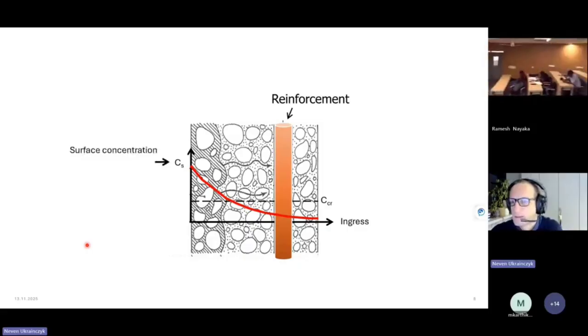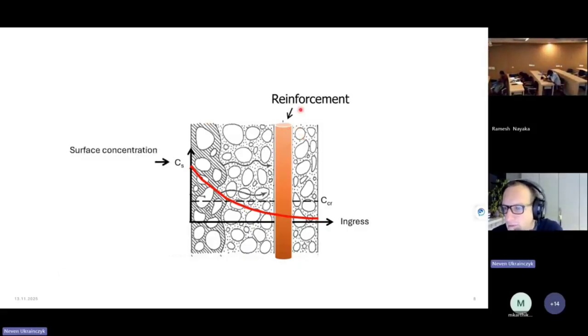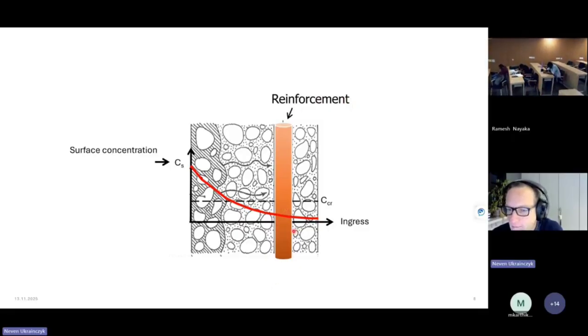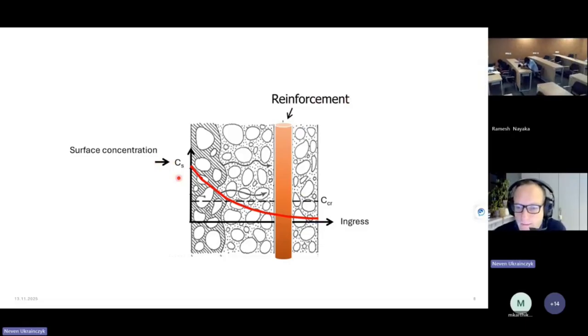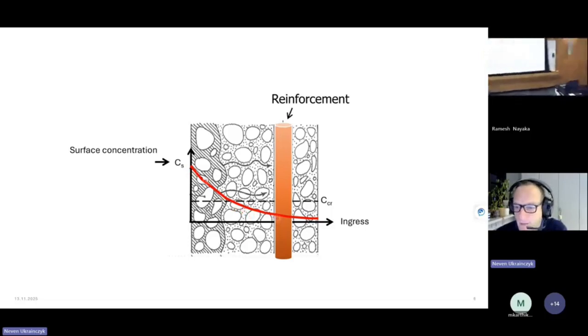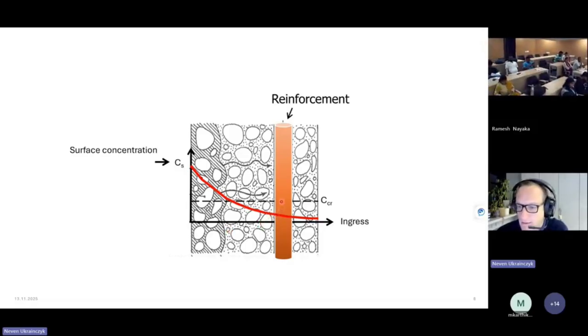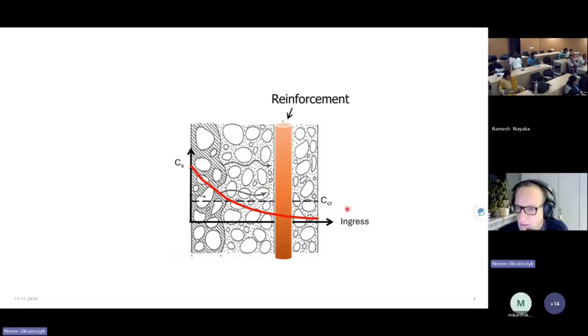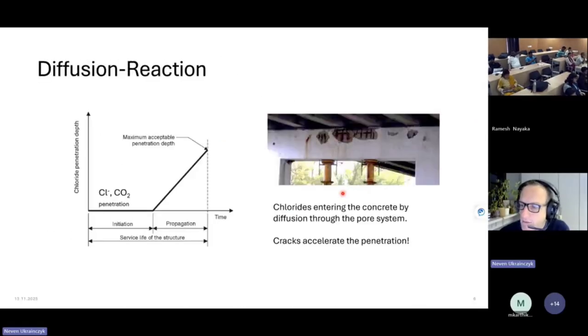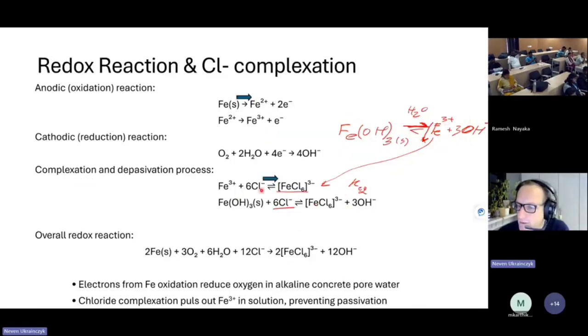So here the picture of the reinforcement. So the rebar reinforcement bars, steel bars, and here we can see we have the surface concentration, and then how the chlorides diffuse inside the concrete, and here we are reaching some critical threshold. This is the critical threshold when the steel starts to become depassivated, and now you know that this actually also depends on the pH. So this critical threshold is a function of pH, and you know why. Of pH and of chlorides. So it's not only, I mean, in standards we have the critical threshold for chlorides, but this is actually also pH dependent, and you know why now.